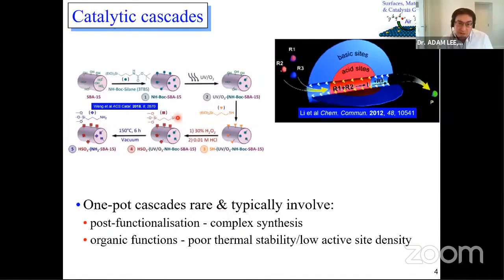You can actually see this here. This is an organic acid, a sulfonic acid. And because we're using organic functions in many of these, they offer poor thermal stability. We can't heat the catalyst to high temperature because they decompose. And we also often have low active site density. We only have very few of these acid groups in our catalysts, so our activity is low.